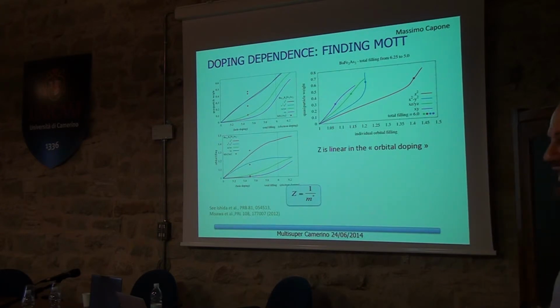So I neglect the total density, and then I have something like this, which tells you what? Here you see that the Z of each band goes linearly in the density of that orbital. So in each band, everything is controlled by the doping of that band. This story of doping the Mott insulator comes back here. So if you want to know why a band is correlated or not, the answer is because the individual filling of the band is closer or farther from the Mott state. Okay, so this is really like a compass to understand a complex situation.